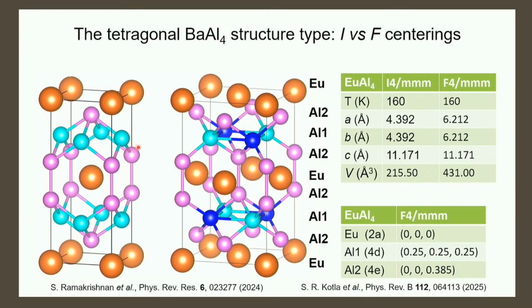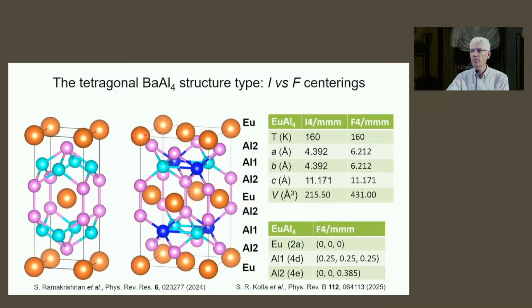For tetragonal I4/mmm, we can also do F4/mmm. That's just a different setting, taking the diagonals. So now, instead of 4, it's a 6 angstrom unit cell. That is this diagonal and this diagonal, and otherwise the structure is the same. It's a different setting. That means F4/mmm you don't find in the International Tables, because it's not a different group. The structure is quite simple: europium, fixed position; aluminum 1, fixed position; aluminum 2, one free parameter.